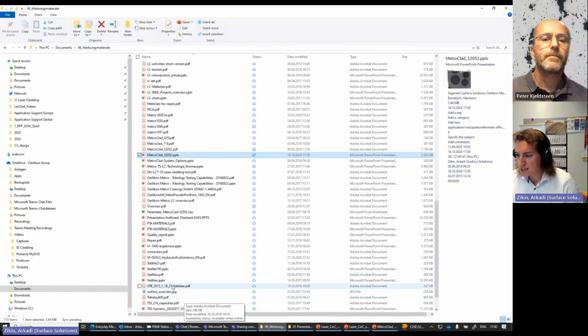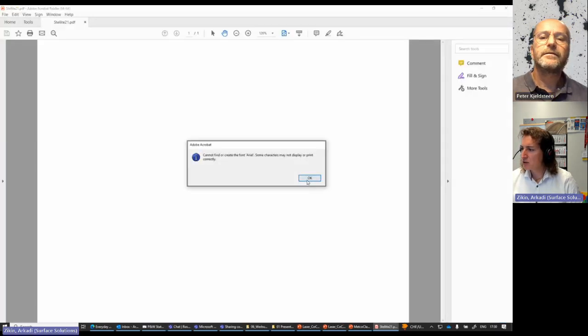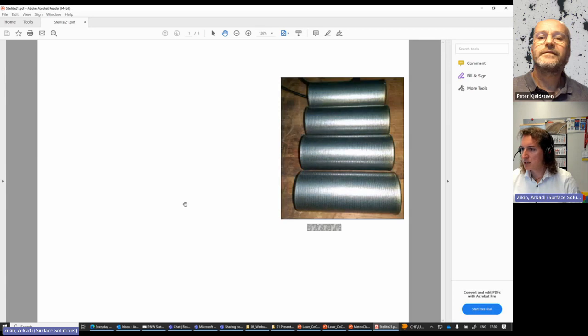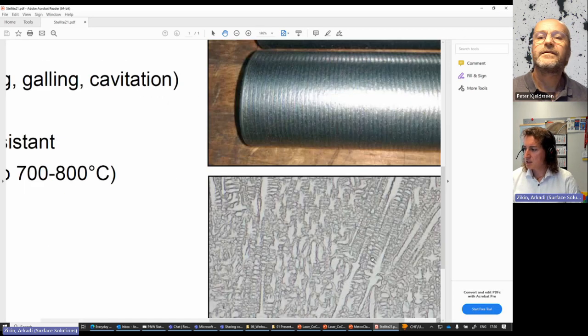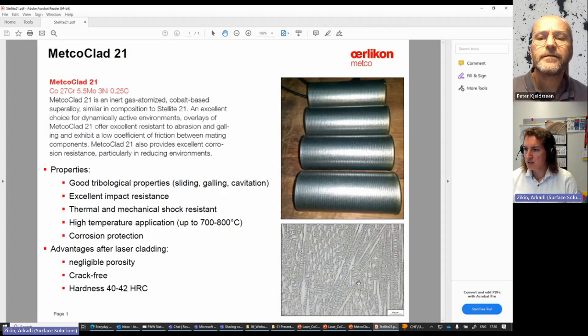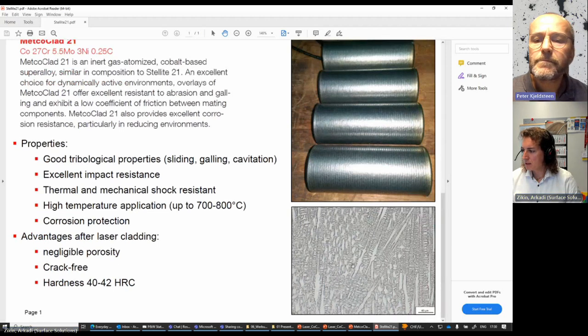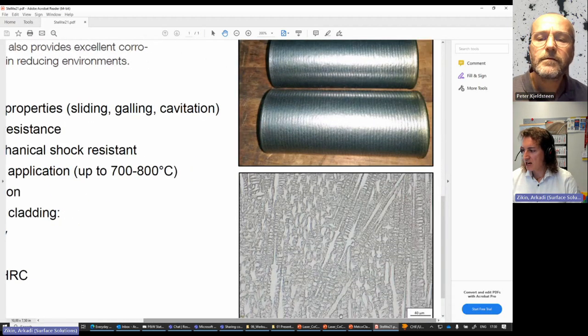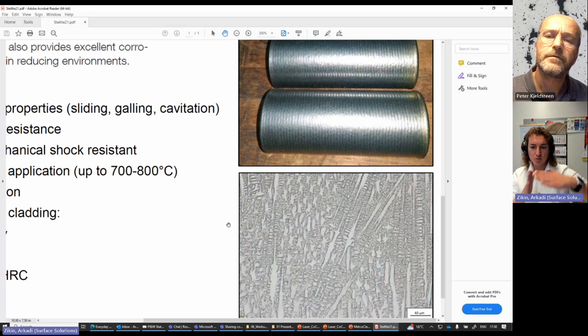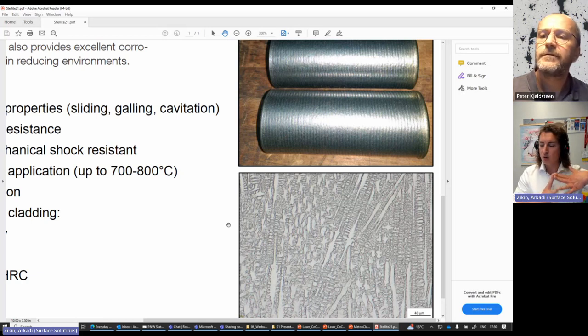I can probably give you an example more on a, let's say, stellite example. I don't know why my PowerPoint is not working properly today, but here. If you look at a stellite, like Stellite 21, it has a typical hypoeutectic structure, dendrites everywhere. So you get it in a way similar to casting. The difference with laser cladding, due to low heat input and extremely rapid cooling, is that your microstructure is 10 to 100 times finer compared to casting.